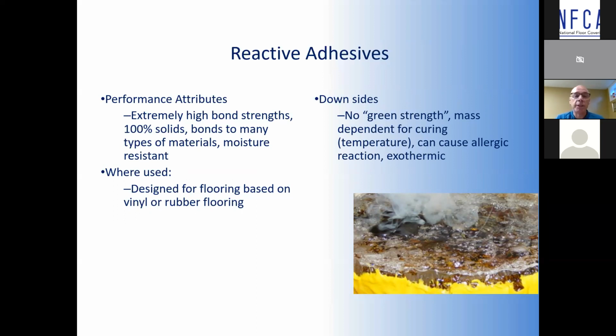There is a downside, particularly to the epoxies. They can cause allergic reactions. They're exothermic, so these can be very, very difficult to work with, particularly if you leave them in the bucket. You can see in that picture a melted bucket from using an epoxy and not taking it out, because the bigger the mass, the faster they cure and the hotter they're going to get. They have no green strength. In other words, when you first put them in, they don't have a lot of strength, and so a lot of times you're going to have to weight down the material and let them build their strength. So they can be a little more challenging to work with from an install standpoint.